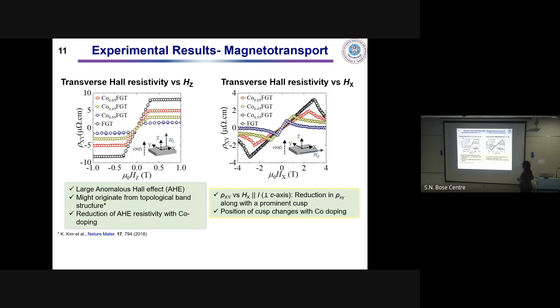Now, what is interesting is that when we have measured the transverse Hall resistivity when the magnetic field is applied in the plane of the sample, in the x direction, what we have observed is a very striking feature: the transverse Hall resistivity first increases with magnetic field, and it shows a prominent cusp-like feature, and then there is a reduction. And the position of the cusp changes with cobalt doping. So this is quite uncommon behavior that we have observed, and that also matches with the first theoretical prediction of possible existence of topological spin textures in Fe3GeTe2.